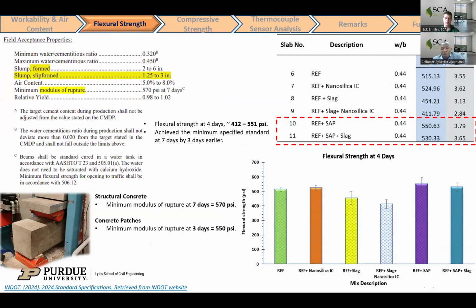So we were able to evaluate the flexural strength at 4 days, and the range we had was between 410 to 550 psi. From the INDOT standard, the minimum modulus of rupture for 7 days is 570 psi for structural concrete. But we had 550 psi at 4 days.